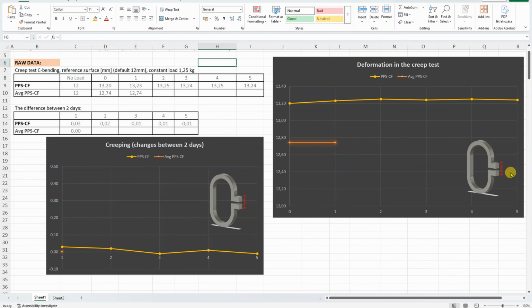On this graph we can see the distance between two reference surfaces, and we can see bigger deformation on this tested PPS compared to the average PPS-CF, but the creeping is the difference between 2 days, and that's presented on the second graph, and we can see it jumping up and down a little bit, but this is just inaccuracy in measuring. This creeping is extremely minimal compared to almost any other filament type.